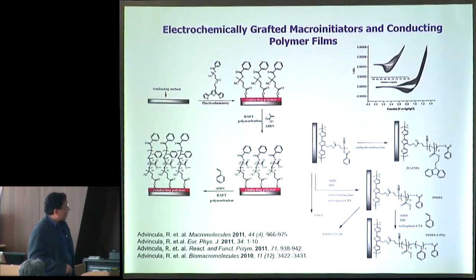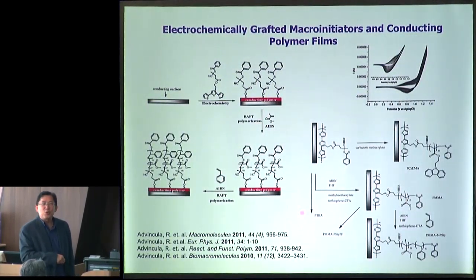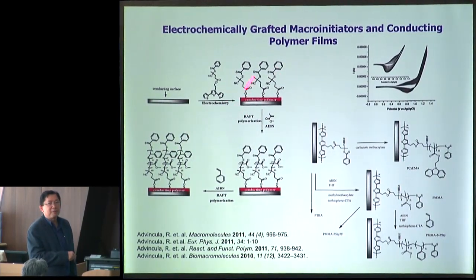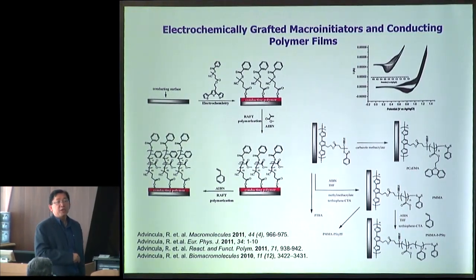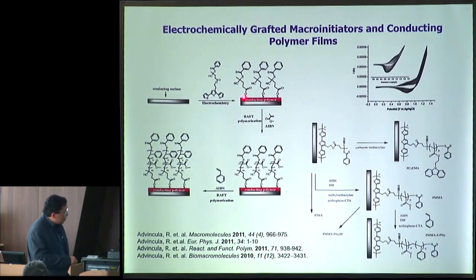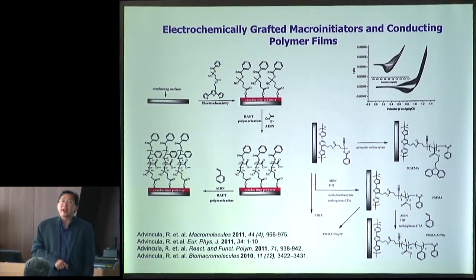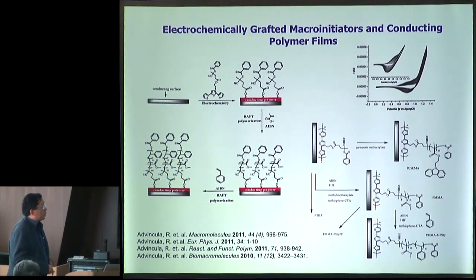So anyway, to continue some of that work, we took this type of chemistry. We designed what we call an electropolymerizable macroinitiator. So here you have a conducting polymer that is formed by the reaction of this thiophene, but at the same time it contains a RAFT chain transfer agent for RAFT polymerization. So we would pattern or deposit this conducting polymer. We can grow a polymer brush, in this case PMMA, and then a block with polystyrene. So you can easily make these electrografted or electropolymerizable macroinitiators.